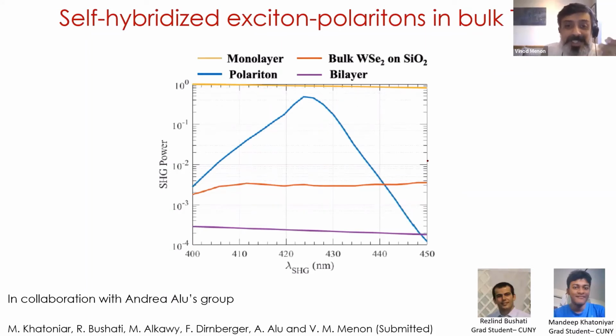I must point out that what you get from the monolayer is actually, although the theory shows that it is lesser, experimentally what we see is that it's actually slightly better in the polariton case than in the monolayer, at least at low power levels.